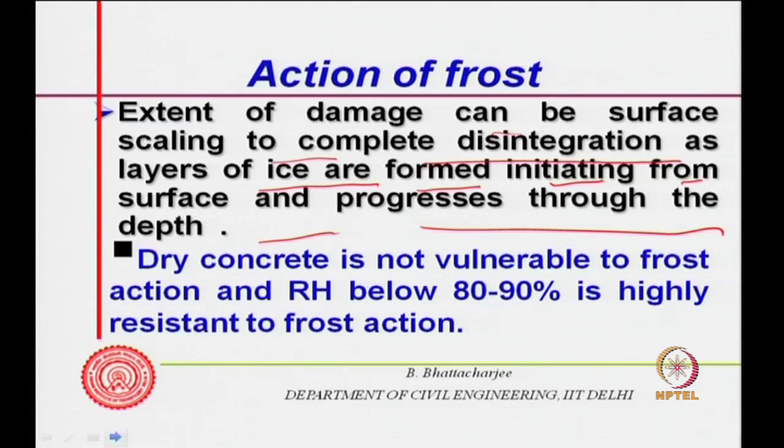If the concrete remains dry, it is not vulnerable to frost action, because RH below 80% to 90% is highly resistant to frost action, because water is not there, what is there to freeze. So, if the relative humidity is less than 90%, only vapor should be there and it will not freeze. So, dry concrete is not vulnerable to frost action, very, very important. Therefore, again we see if we keep water out, everything is fine.